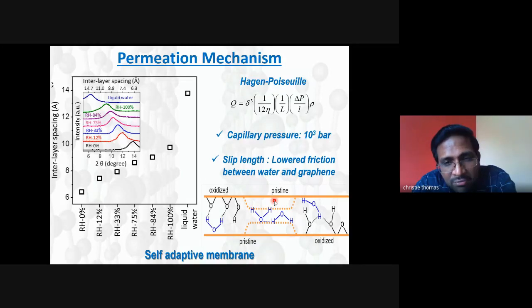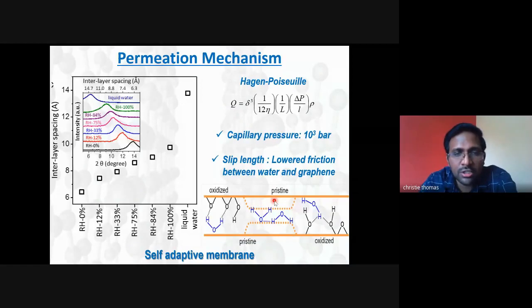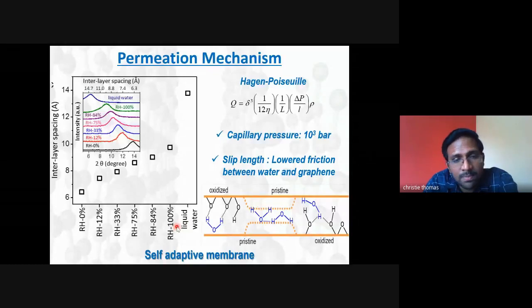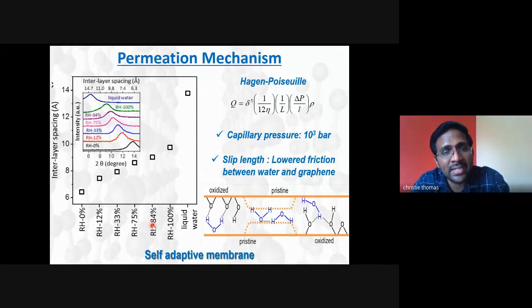That means the graphene oxide membrane has been kept at different RH, including liquid water. RH means relative humidity. As the humidity increases, the interlayer spacing increases, which you can clearly see here. And in liquid water, the interlayer spacing goes up to 14 angstrom.